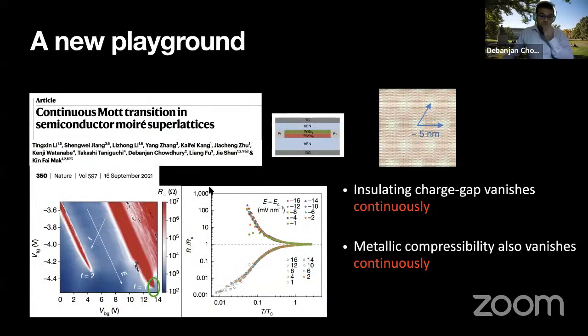Okay, so this brings me to the recent experiments. I'll just summarize all the key features in 2 slides. So this is what the transport data looks like. So red is very high resistance and blue is low resistance. And the amazing thing about these systems is that this is a bilayer of 2 different materials which have a slight lattice mismatch, which gives you this Moiré pattern with a long length scale that's roughly of the order of 5 nanometers or so.